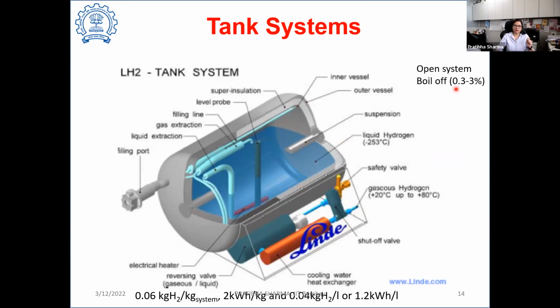Depending upon the system size, that can range from 0.3% per day to 3% per day. And this is enormous. If you have a liquid hydrogen tank being filled in a container and you leave it for a few days, go for a vacation, and come back after the vacation, you may find the tank empty. So that is the biggest challenge, boil-off, as well as the high energy intensiveness of the process. And that is the term dormancy, which we introduced in the first slide: for how long it can be kept in the liquid form without evaporating, that is, without release of hydrogen from the system.